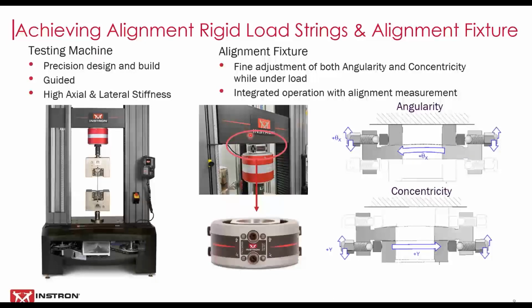So we go to rigid load strings. The first thing when we're using rigid load strings is we need a precision built guided testing machine with high axial and lateral stiffness, because it's no good having a rigid load string in a machine that is itself not rigid. In this case, you can see an electromechanical machine with large diameter ball screws, with guidance columns inside these covers here. So a very nice, big stiff crosshead, and a nice big stiff load cell as well.